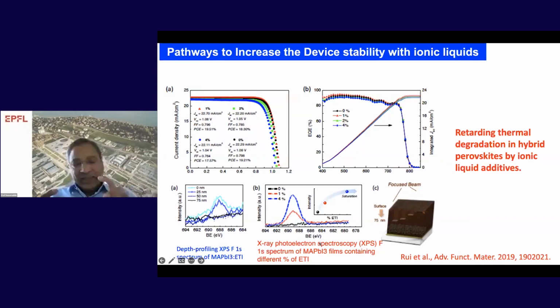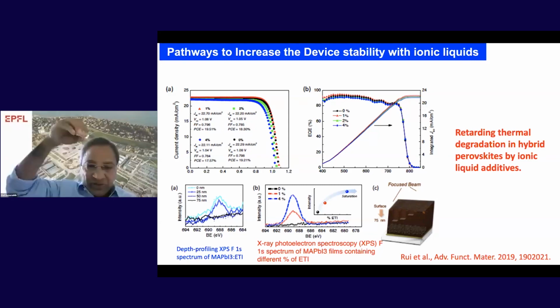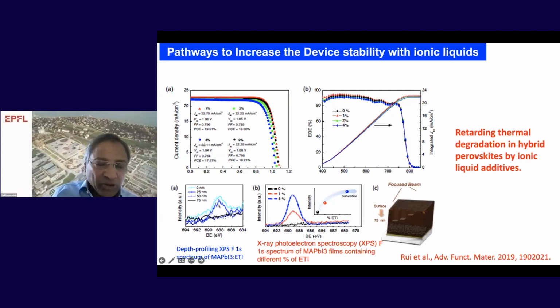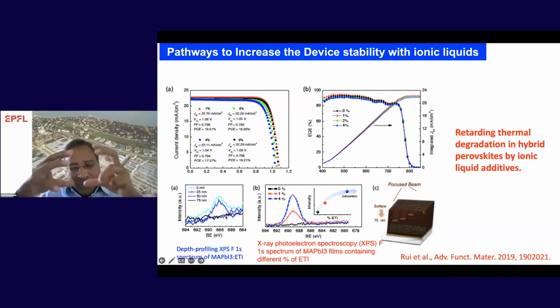Now we have taken our perovskite composition, and with the focused ion beam, we etched from the top to bottom. So at zero nanometers, you can see the fluorine binding energy at 688 eV. And if you go up to 25 nanometers, with the focused ion beam digging into the perovskite grain, you can see still the presence of fluorine binding energy. After 50 nanometers, there is nothing. So that means this ionic liquid is forming a shell on the top of perovskite grains.